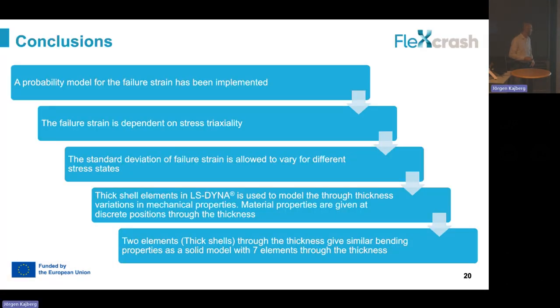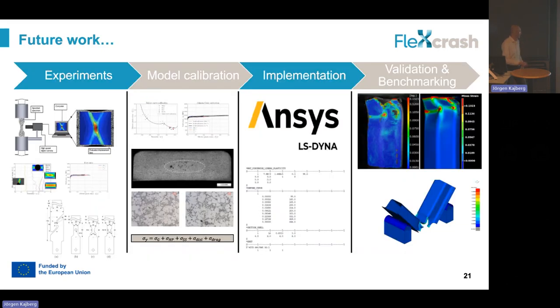If you look at some of the conclusions, the probability model has been implemented. You need to include the stress state dependency. The standard deviation at different stress states can be taken into account. Thick shells are very efficient for this kind of structures, and we think 2 elements is enough through the thickness. The next step and future work will be calibration of this model. That's the next step. So I think I will stop there.